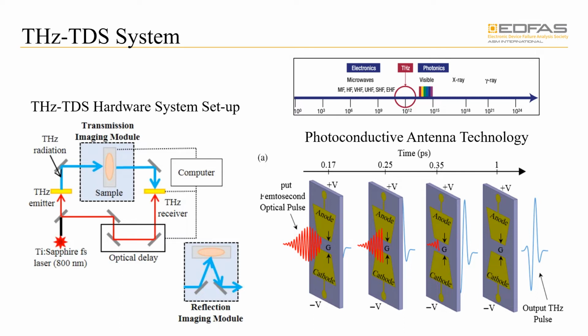So here we have a diagram of the terahertz TDS system setup. Here we start from the femtosecond laser pulse, and this pulse is split by a beam splitter into pump beams, which is the blue line, and probe beams, which is the red line. The ultrafast pump beams will reach the terahertz emitter, and the optical pulse will be converted into a terahertz pulse. After propagating through the sample, the terahertz pulse will refocus onto the terahertz detector.